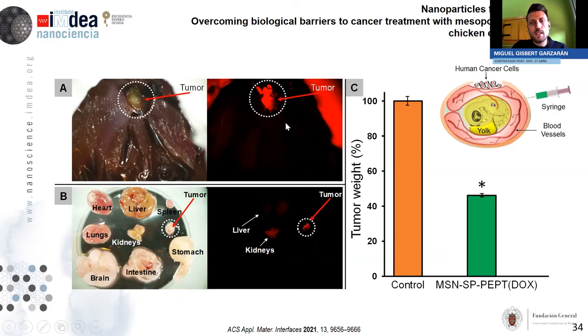Okay, so after checking that the nanoparticles could accumulate in the tumor, we loaded the nanoparticles with doxorubicin, and then we did a tumor elimination experiment. And as you can see here, it is clear that in the case of our complete system loaded with doxorubicin, we could reduce the weight of the tumor, which was a macroscopic tumor, quite big, by 50% in just 72 hours.